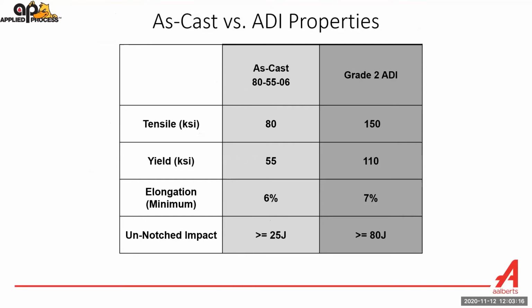So this is a powerful example of, you can take 80-55-06 ductile iron, which is probably the most common grade of as cast ductile. If we were to austemper it, we almost double the tensile strength. We double the yield strength. The elongation actually goes up from 6% to 7%, and then the unnotched Charpy impact more than triples. And again, the reason for that is we've created a different crystal structure in the matrix of the material.